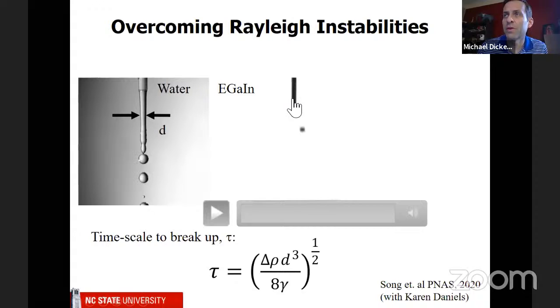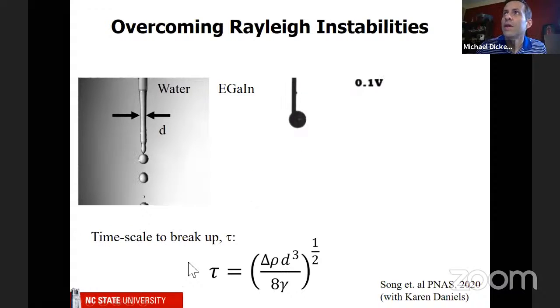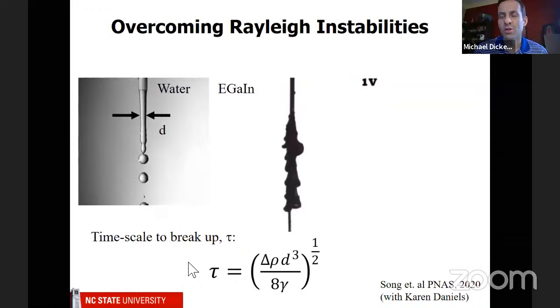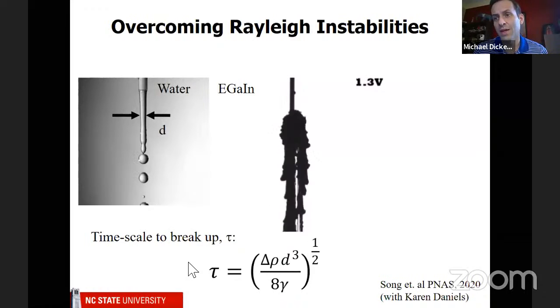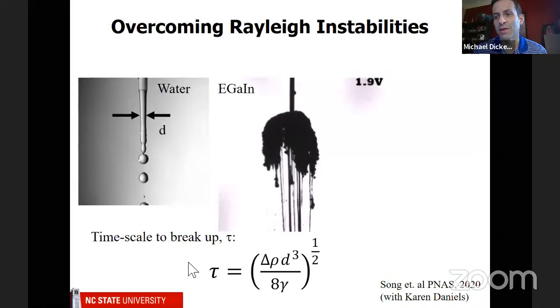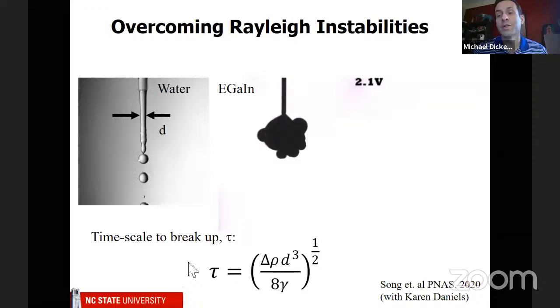So when we pump the liquid metal out, you're going to see it's going to form droplets. However, as we start applying a voltage, you'll see that the droplets get smaller because the tension is going down, and smaller and smaller, until eventually at that magic voltage, about 0.8 volts, it comes out as a wire. And then if we apply too big of a voltage, we get a really thick oxide layer, and it actually starts behaving like candle wax, which is interesting, but we haven't really studied that. We've really studied just the formation of that wire.